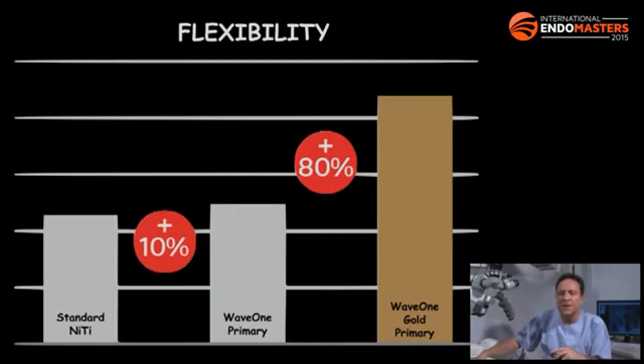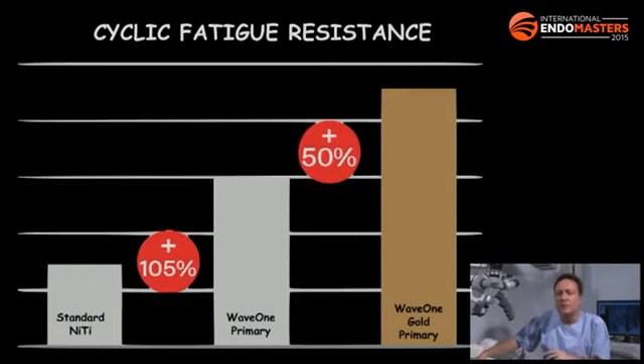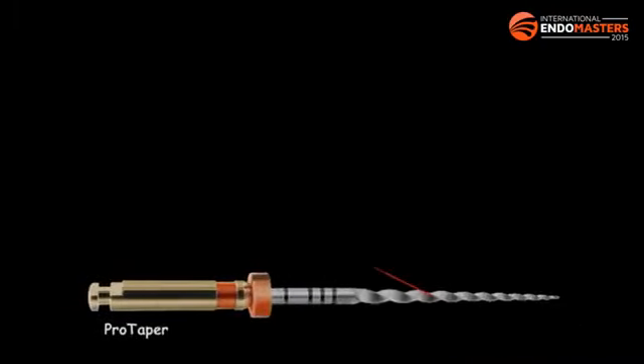And if you see here this graph and you compare Wave.One Primary M-Wire with Wave.One Gold Primary, we are up to more than 80% more flexibility of the Wave.One Gold. Again, if we compare cyclic fatigue resistance with the primary, we have almost 50% more cyclic fatigue resistance when we compare Wave.One Primary with Wave.One Gold Primary. And again, it's not only the gold wire, it's always the combination of the alloy, the combination of the cross section, and the combination of diameters and tapers that make the files more safe in this case.